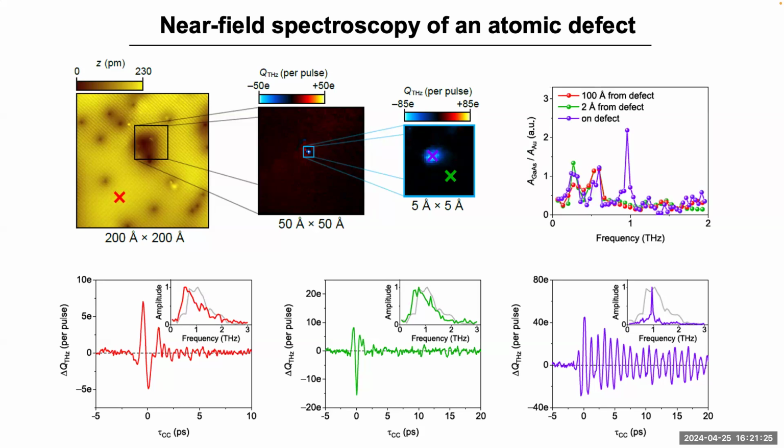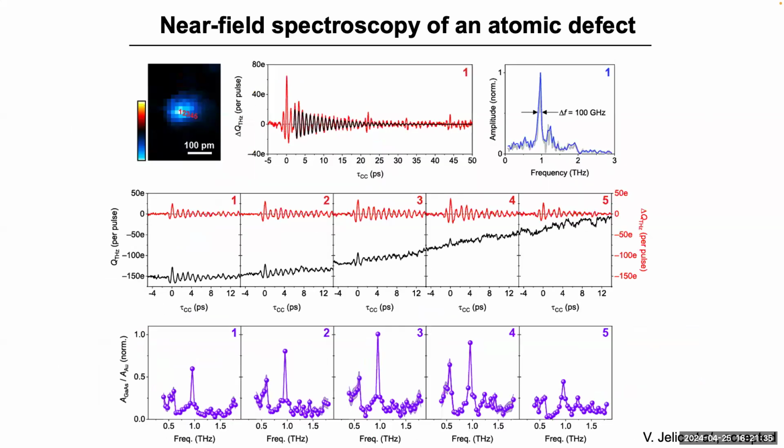So we can compare by taking the Fourier transform of this field in the time domain and dividing by our reference with gold, and we can see what basically the spectra look like. And then we can even zoom into this thing. We can take spectra as a function of space, now we're into picometer scale, and zoom in on this scale. We can really measure what's the Q factor of this thing? Where does this resonance evolve, and then where does it go away?